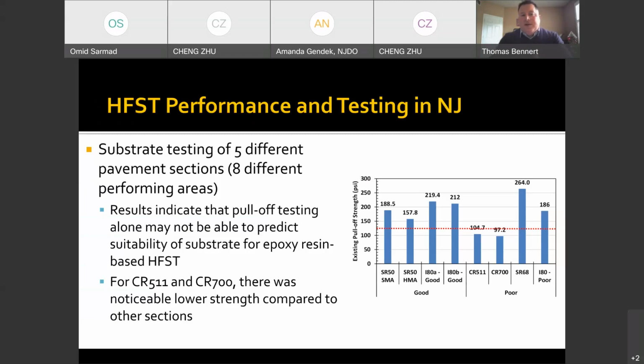Just to give you an idea of some of the pre-screening results that we've seen. So we took a look at approximately 8 different sections across the state with varying degrees of performance. You can see from the figure there's 4 sections that were performing well. And there are 4 sections, including those county road sections that I showed earlier, that were performing poorly. And what we first looked at is the pull-off strength. So we look at it and we can clearly see that in the good, it met a certain threshold. In the poor, 2 of them were below and 2 of them were above.